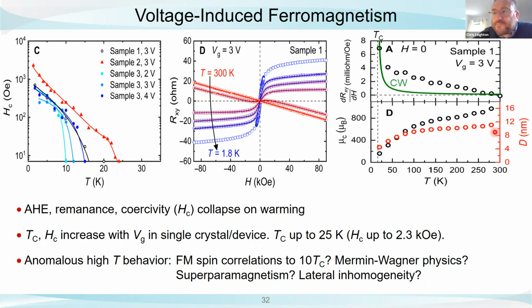Where can it come from? We have a vapor transport crystal. They have terraces. The terraces are a bit wider, actually, than 10 nanometers. They're typically something like 100 nanometers. That could be part of it. The other thing is, like almost everybody in this field, we take an air-exposed surface and we put the ionic liquid or an ion gel on top of it. So could it be that there are lateral inhomogeneities and we have little bubbles in there that are regions where it's better gated than others? I think that's certainly possible. So that could be producing the lateral inhomogeneity too.